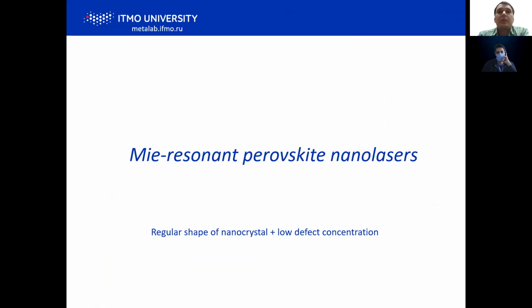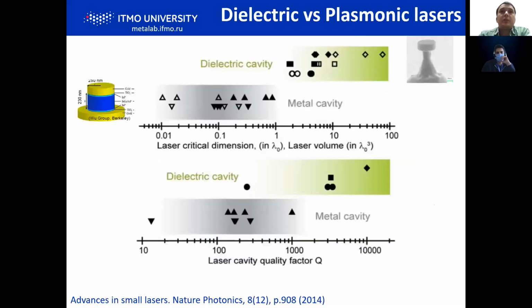But the most interesting thing, in our opinion, is to use Mie-resonant perovskite nanoparticles to create the smallest possible lasers for the visible range. For this case, we need a regular shape of the crystal to have good optical properties, and low defect concentration to have a higher quantum yield. And you may know very well that for lasers, there is also some kind of competition between two approaches: dielectric or semiconductor lasers and plasmonic lasers.